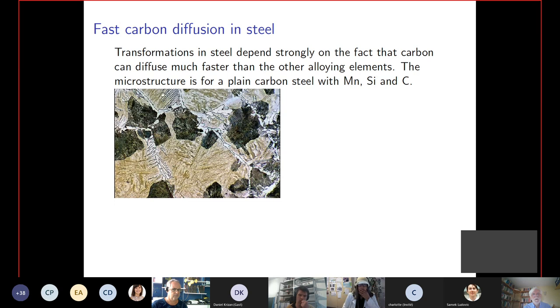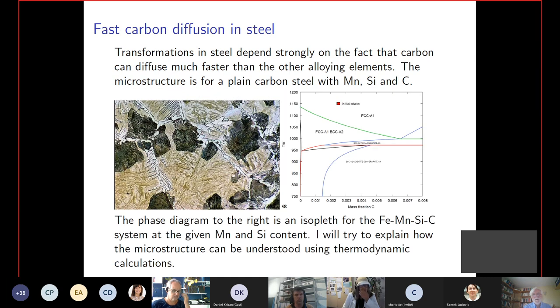This is a low alloy steel. You have a little manganese, 1%, a little silicon, and you vary the carbon content. And the properties of steel are very dependent on how you heat treat and how you modify the cooling, for example. So for this type of composition, you can calculate a phase diagram like this.